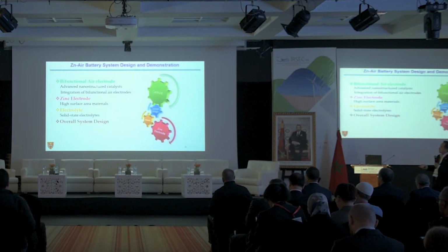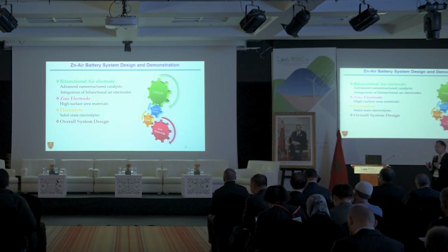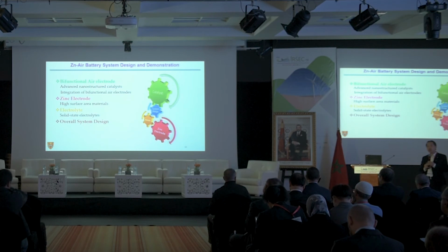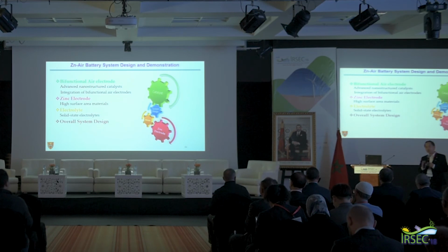So in the past 10 years, based on today's talk, for the bifunctional catalyst air electrode, I think we are ready. We solved that problem, and we can easily scale up by one of these methodologies we are using. And for the zinc electrode, we also put a lot of effort into suppressing zinc dendrite formation, and we found some very useful methodology. We can suppress the zinc dendrite formation successfully, and the zinc electrode could last for more than 1,000 cycles. So the zinc electrode problem is also almost solved.